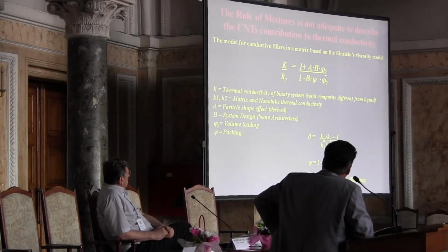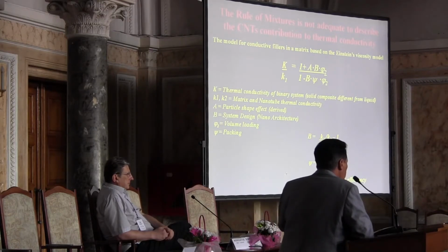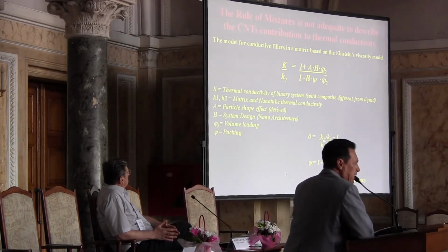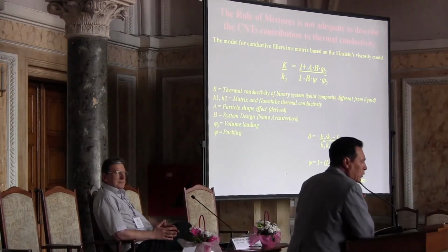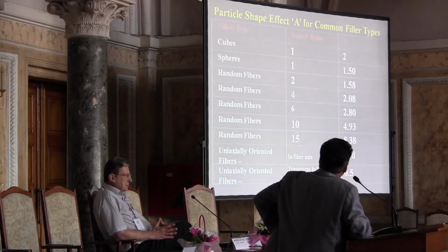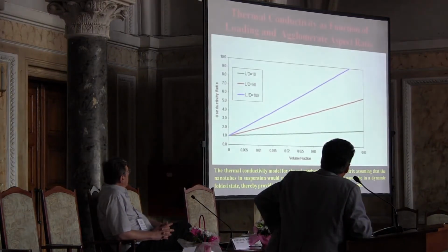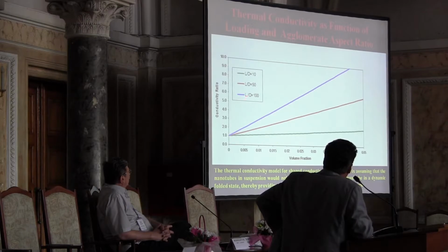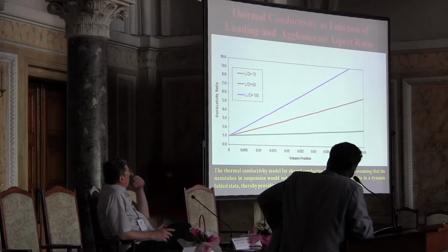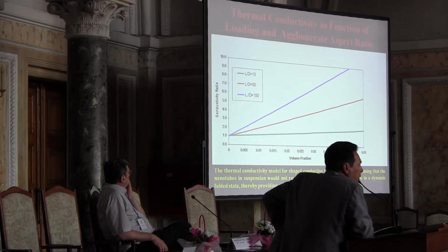I don't have time to go over the modeling in here, but what we are realizing is that the thermal conductivity of the fluid is a function of the agglomerate size, of course the number of the agglomerates because it's a function of the load, and the aspect ratio of this agglomerate. So we are moving forward. This is the expression, this is the length of the agglomerate that you are seeing in here, and this is the diameter of the agglomerate. So if you're talking about a thermal conductivity ratio of 2.75 for one load, this means that you are talking about an agglomerate aspect ratio of the order of 100, okay?